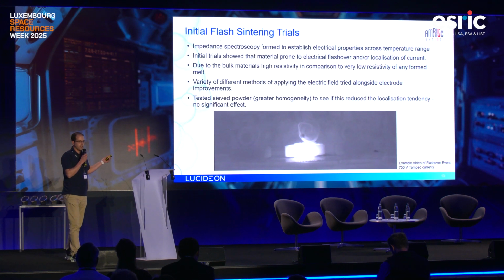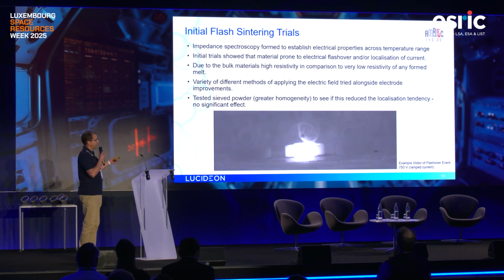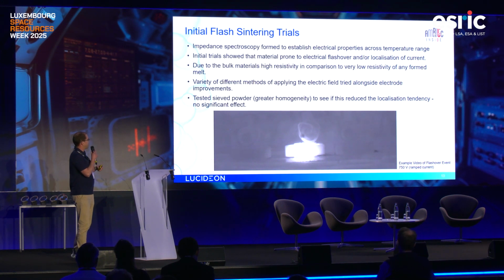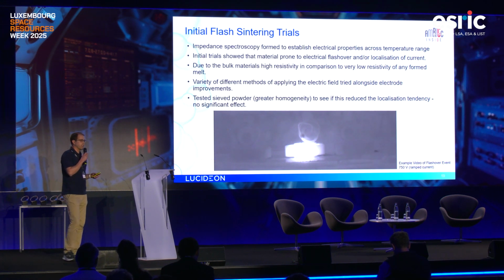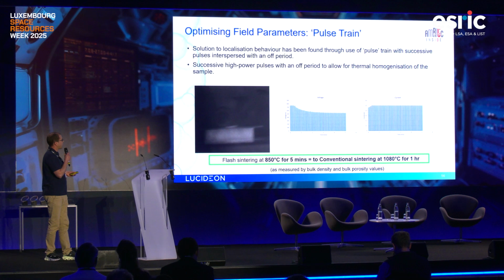So this was at 850 degrees thermal temperature, furnace temperature, sorry. We also tested some sieved powder to see if this reduced the tendency to localize, but it had no significant effect, which is interesting.